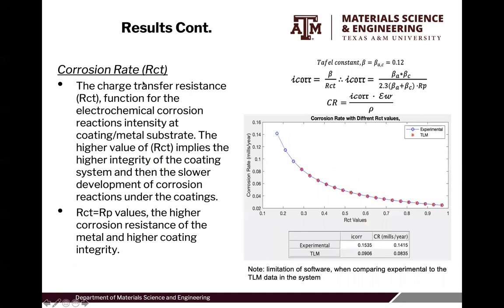For our corrosion rate, using the Tafel constants and the icorr equations, we were able to compute the corrosion rate from both our experimental and TLM data. For experimental data, we had 0.1415 mils per year, and for our TLM it was 0.0835 mils per year. We also wanted to isolate and see what would happen if we increased these values. As we increased our RCT values, which are proportionate to our polarization resistance, we saw a lower corrosion rate.